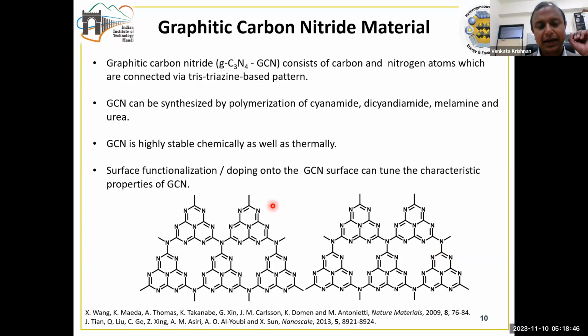And this material, the graphitic carbon nitride, can be easily synthesized by the polymerization reaction, wherein we can use either cyanamide, dicyandiamide, melamine, or urea as a precursor. And also, this graphitic carbon nitride is stable both chemically as well as thermally. So, which means that it can be used as a catalyst for various different types of reactions because it's chemically inert and also thermally stable.